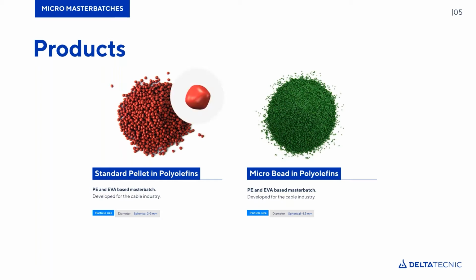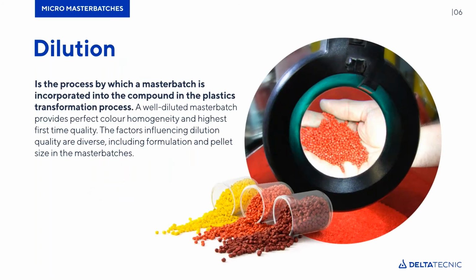This has a round shape, a spherical shape, because it's cut in water, and therefore by contraction due to the temperature change coming out of the extruder head, it contracts and it presents this spherical shape. That's a standard pellet. It has a diameter of between 2 and 3 millimeters, whereas the micro bead, that's what we call the small sized pellet for polyolefins, is just 1.5 millimeters big. Again, the smaller sized pellet melts quicker in the extrusion process, and therefore the dilution process gets accelerated.